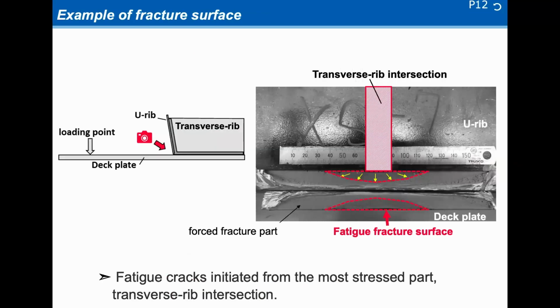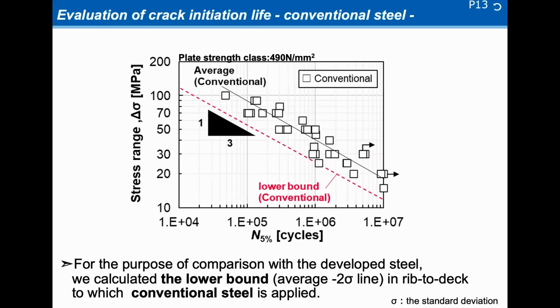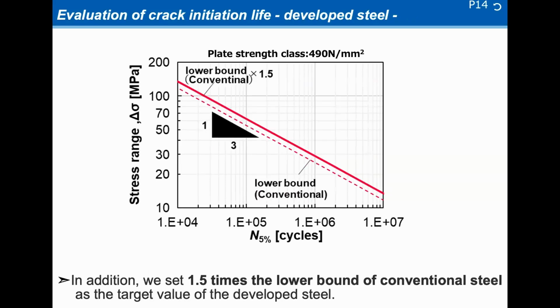This is an example of a fracture surface. Fatigue cracks initiated from the most stressed part, the transverse rib intersection. Finally, the result. This chart shows S-N diagrams when the conventional steel is applied. Square plots show experimental data. For the purpose of comparison with the developed steel, we calculated the lower bound in rib-to-deck to which conventional steel is applied. In addition, we set 1.5 times the lower bound of conventional steel as the target value of the developed steel.